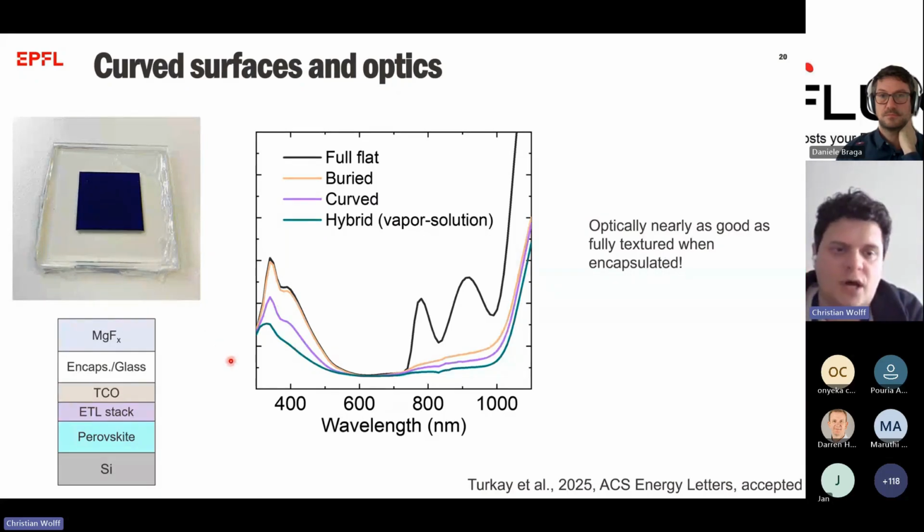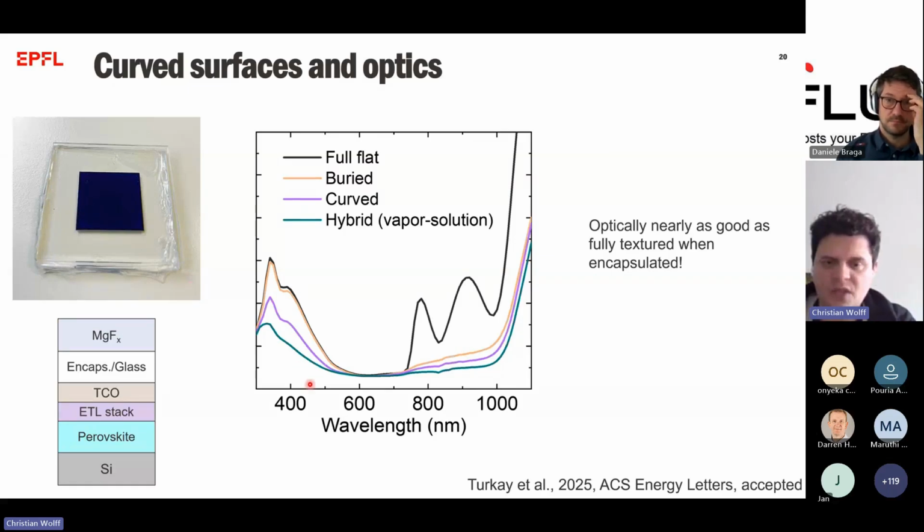Yeah? So if you have improved internal reflection and then a chance to reabsorb, then you should see this by the light not being able to be emitted from the overall stack, but being absorbed at least somewhere in the stack, without thinking about where for the moment. And so this is a very simple experiment, right? You just go to the UV-vis spectrometer and measure the reflectance. That's it. And we did this for the four devices, or four structures, that I mentioned earlier.